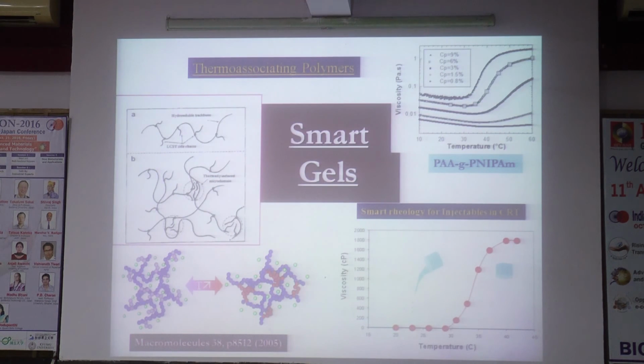So that's why it's called a smart gel. That means at room temperature, it's a liquid. At about 40 degrees centigrade or 37 degrees centigrade, it forms a gel. So it transforms from liquid to gel, and that's why they are used as smart polymers, and they are used in injectables in drug delivery applications. Like for example, you take this polymer and put the drug in the solution and inject into the body. The body temperature is 38 degrees or 37 degrees centigrade. So at that temperature, it forms a gel, and the drug is released at a constant rate. So of course, there are so many questions that need to be asked about this phenomena. A lot of research is going on injectable polymers for drug delivery applications.